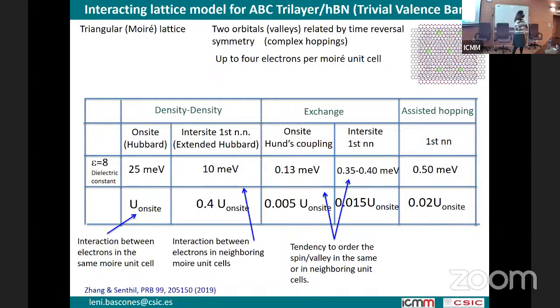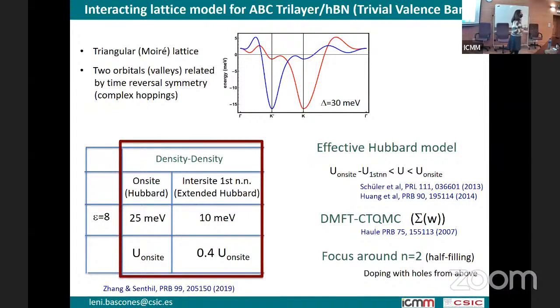They also quantified interaction to first nearest neighbors. And there are also other smaller terms, which are exchange terms, Hund's coupling, and so on, or assisted hopping terms. What you can see here is that these exchange interactions, whether on-site, this Hund's coupling, or between different sites, are much smaller than this density-density interaction. So what this suggests is that in a first step, one can just keep the density-density interactions, see what happens, and later one can consider the other terms.